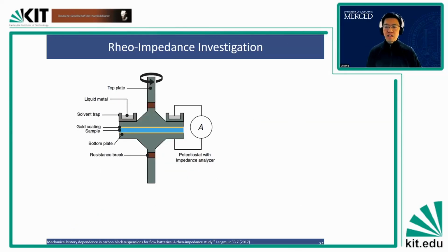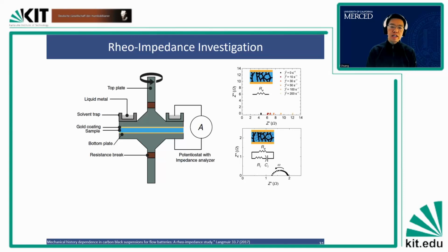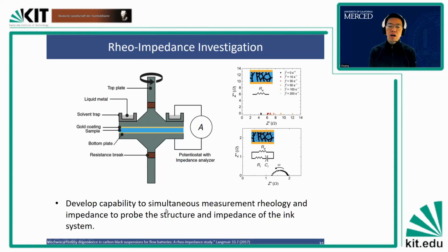Recently, we expanded this study to not only study rheology, but also impedance in situ, or simultaneously. So we developed and modified our tools to implement this rheo-impedance investigation of the ink, because we know all of our inks have ionic conductivity, and also electrical conductivity. Through this study, our goal is to understand what the electrically conductive microstructure looks like, what the ionic microstructure potentially looks like, and what their interactions are through probing them at different conditions. Right? So these are the tools that we use to study our microporous layer and also our catalyst layer ink.